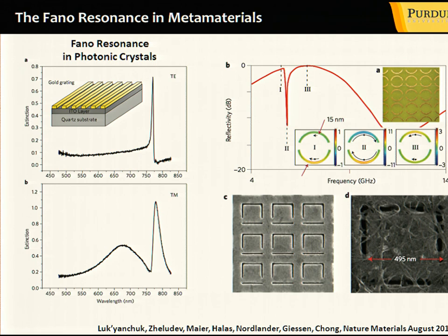Well, speaking of interference, there is lots of activity related to the so-called Fano resonance, because it's a classical interference effect. Normally, it involves a broadband, typically low-quality resonance, and a very sharp resonance, typically a dark mode. Because of the interference, you could have extremely sharp structures. This, for example, is a structure where you could have interference between propagating surface plasmon polaritons in these periodical structures and localized surface plasmon excitations, and you have this Fano resonance.